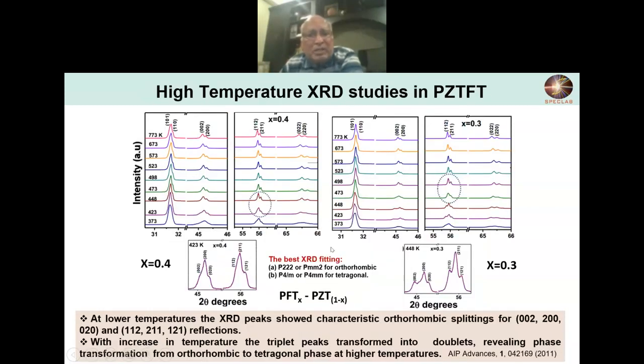We tried to study the X-ray spectra at high temperatures as well. Here is an example I'm giving for PZT-PFT. The XRD spectra showed these triplets. If you resolve them with slow speed, you get something like this. And here, you will get something like that. In other words, there are three peaks.